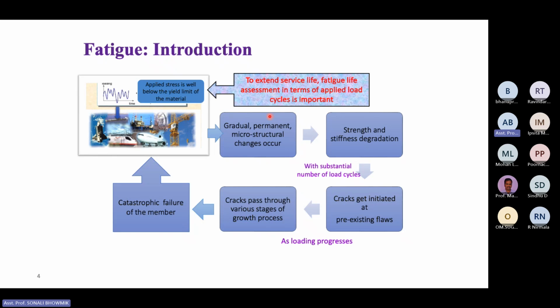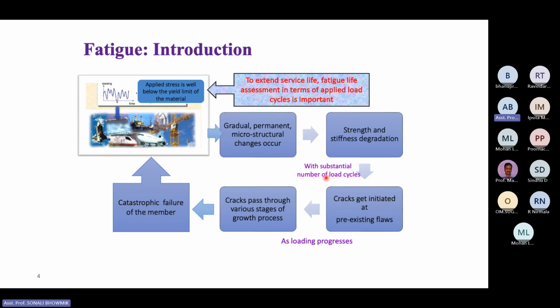So these are very crucial phenomena for structures subjected to fatigue, repetitive kind of loading, and for structures which are heterogeneous in nature. It is a gradual, permanent process, due to which there will be strength and stiffness degradation. As the number of cycles increases, the repetitive loading intensity will increase, and from the pre-existing flaws the crack will get initiated, or the existing micro cracks will accumulate, and finally a major crack will develop and catastrophic failure will occur.